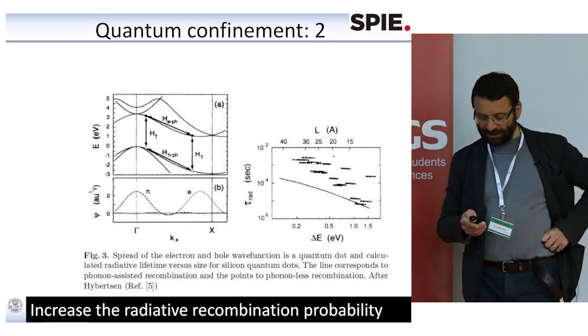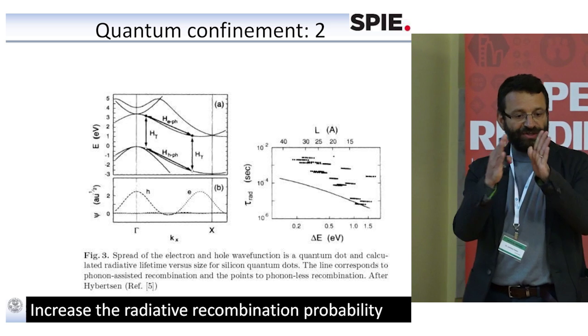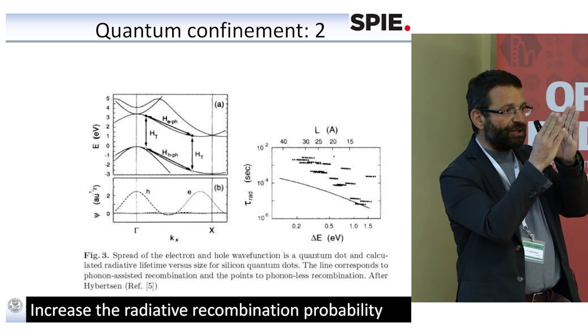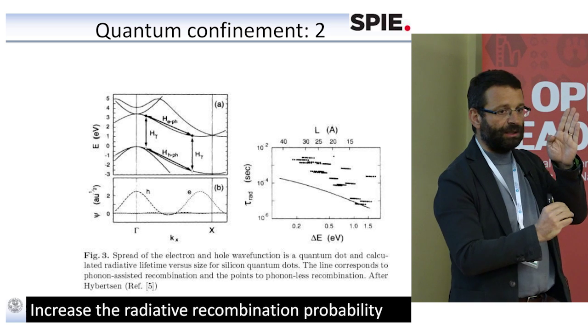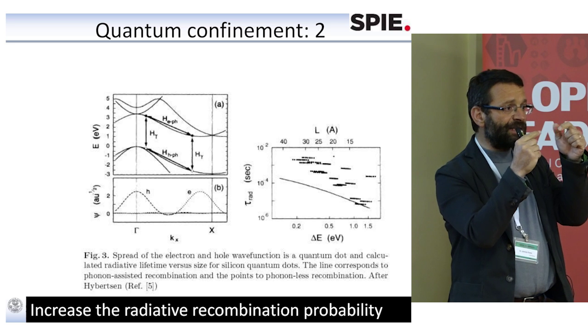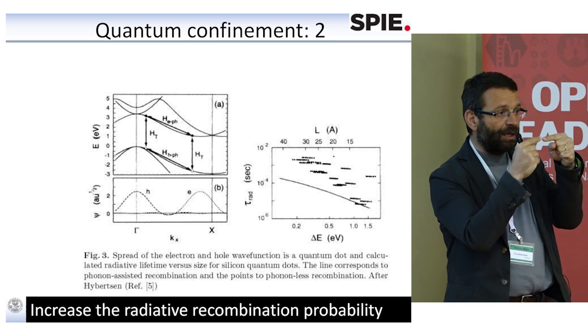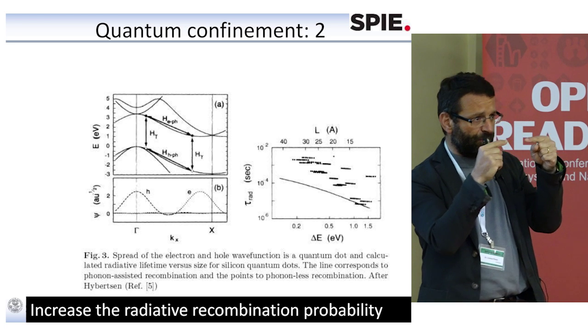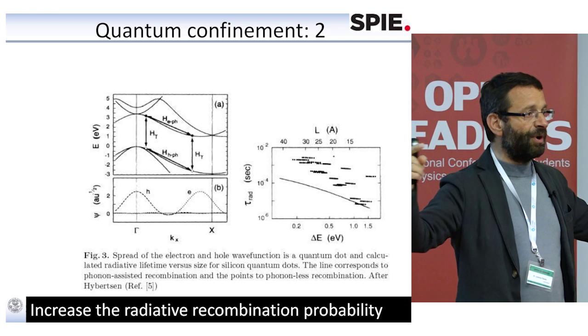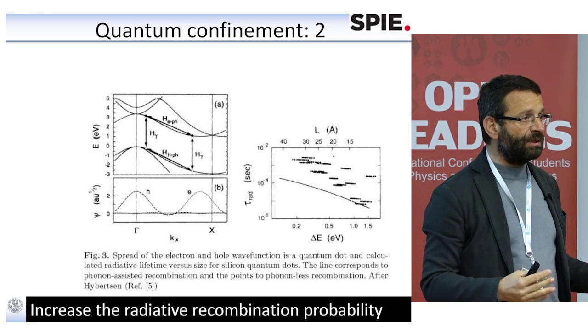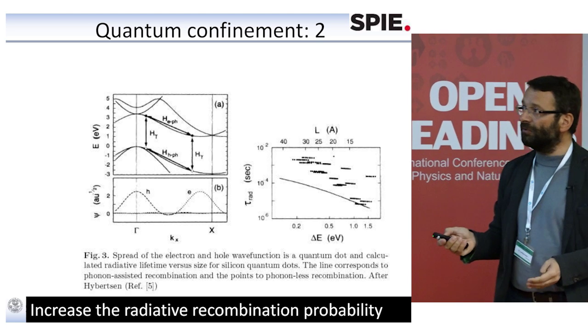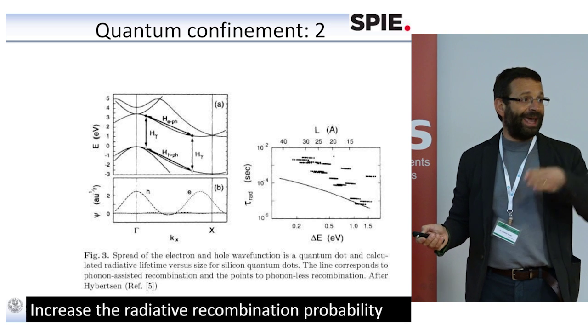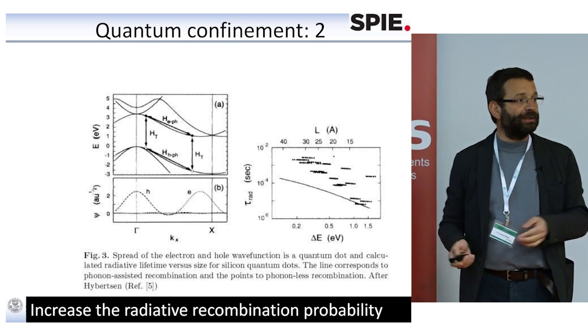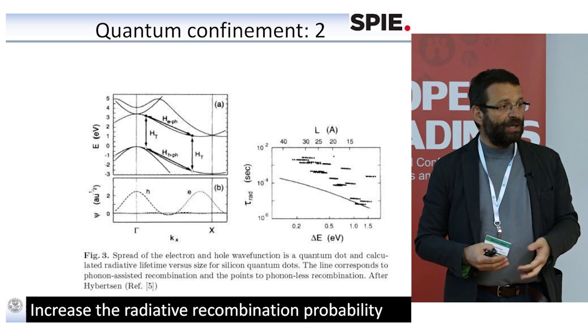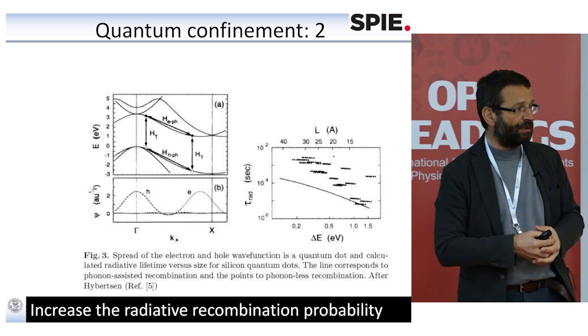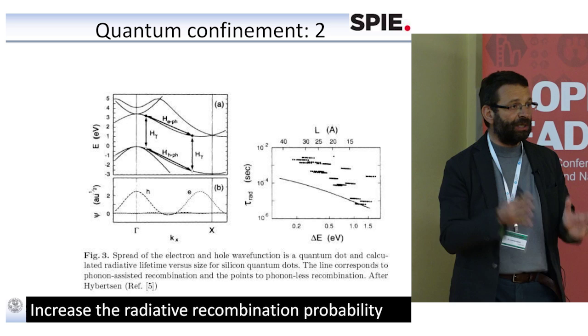The second consequence of quantum confinement is that now you squeeze the wave function, the electron and the hole wave function, within the nanocrystal in real space. But the Heisenberg principle tells you that if you reduce the wave function in real space, you broaden the wave function in momentum space. Broadening the wave function in momentum space means that now the overlap between the electron that is confined at the X point of the Brillouin zone and the hole that is confined at the gamma point of the Brillouin zone is increased. So as a consequence, the direct radiative recombination probability is increased by the quantum confinement effect.